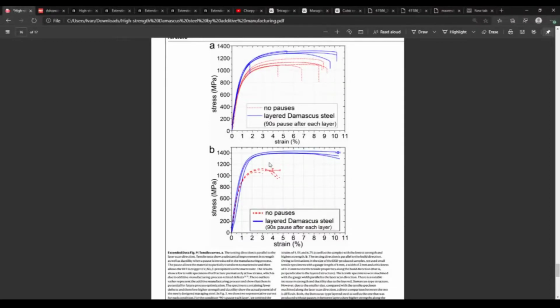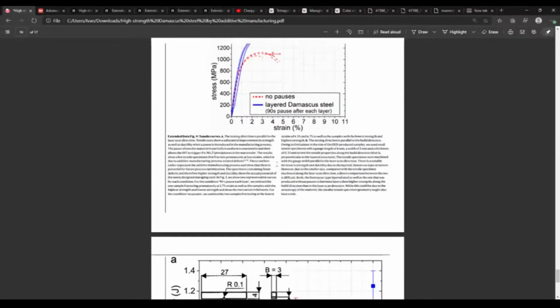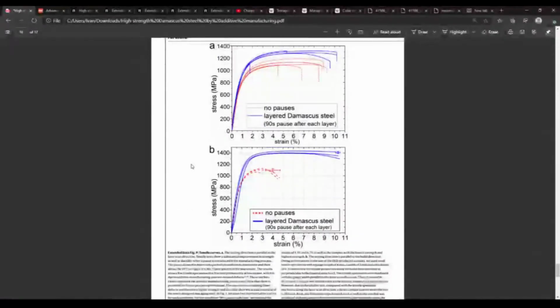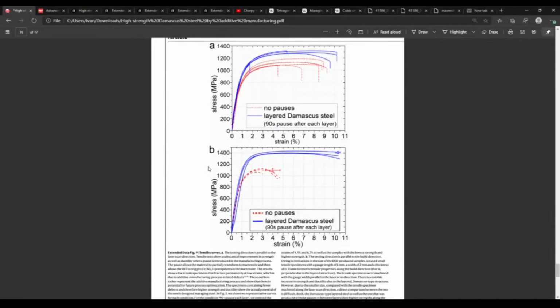Can I just point out that a massive problem with additive manufacturing is inconsistency, how the part takes stress? Yes. With its print orientation, this is for PLA prints in an FDM printer. Prints can be considerably weaker when pulling the layers apart compared to pulling parallel with the part. The bit that I can see there is that the Damascus process really improves that consistency compared to the no pauses. That is fantastic, because it's a massive problem with the manufacture of just any additive process. Yeah.